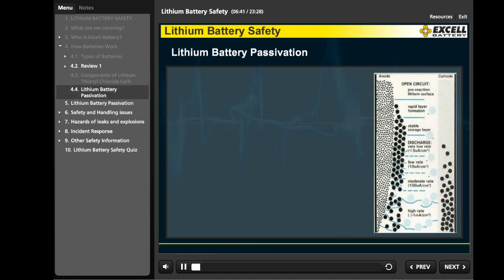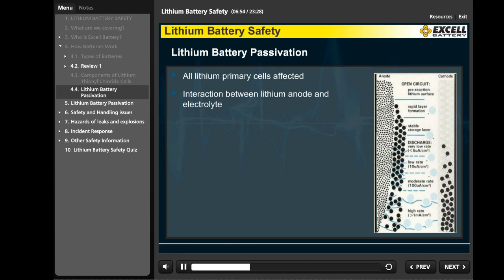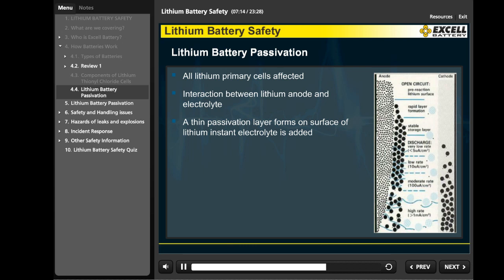Lithium battery passivation. All lithium thionyl chloride batteries, the type described in this presentation, are affected by a phenomenon known as passivation. Passivation is formed as a result of the interaction between the lithium anode and the thionyl chloride electrolyte. This thin passivation layer is formed instantly when electrolyte is added to the cell, and it serves to protect the lithium from corrosion or self-discharge. In fact, the passivation layer is the reason the lithium thionyl chloride cells even exist. Without this layer, the cell would self-discharge at a very high rate or possibly explode. The attachment titled Electrochem Passivation of Primary Lithium Cells explains in more detail how passivation is formed and how users of lithium batteries can work with the passivation layer.